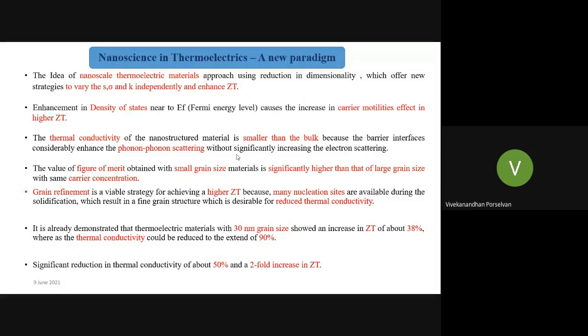So phonons are the phenomenon which we call heat-carrying packets. So in thermoelectric material, we know that if we have more phonons, they are carrying the heat, so it can increase the thermal conductivity. That is why we should reduce the phonon transport. The value of the figure of merit obtained with small grain size materials is significantly higher than that of large grain size with the same carrier concentration. Here, grain refinement is a viable strategy for achieving a higher ZT because many nucleation sites are available during solidification, which results in a fine grain structure, which is desirable for reduced thermal conductivity.